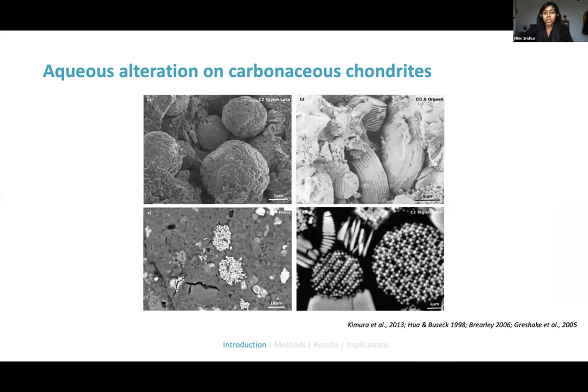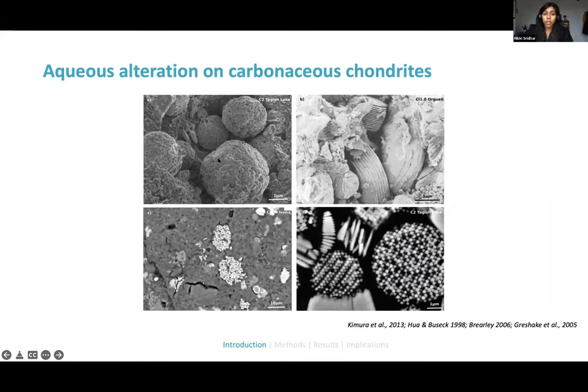What's really interesting about magnetite in particular in these meteorites is that it adopts a range of different morphologies. Magnetite adopts forms such as plaquettes — these stacked disks — as well as framboids, which are closely clustered aggregates of small, less-than-one-micron-sized grains. There are also smaller single grains of magnetite in the matrix of many of these meteorites.